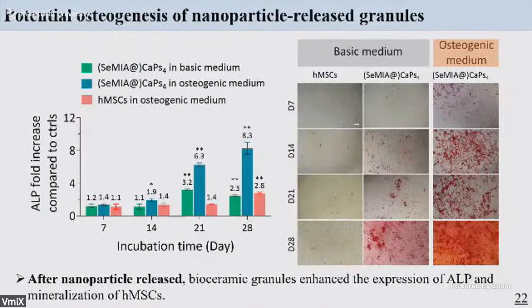After releasing the nanoparticles for 5 days, we observed that almost all nanoparticles have been removed from the granules. And here, the granules could also further enhance the ALP expression and mineralization of the HMSC. This indicates the potential of osteogenesis for bone reconstruction.